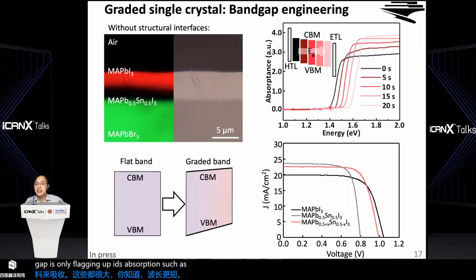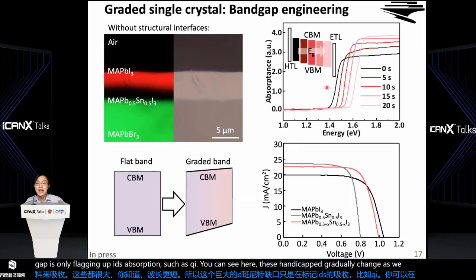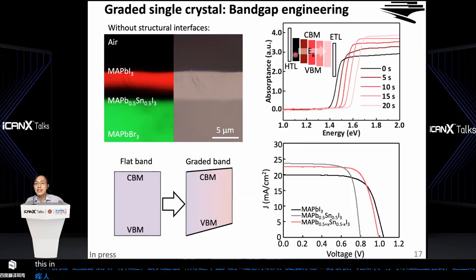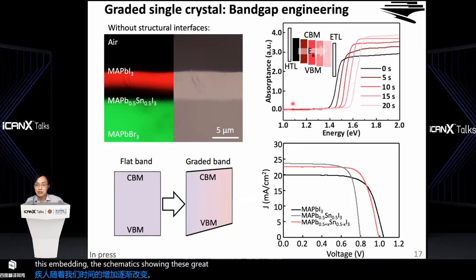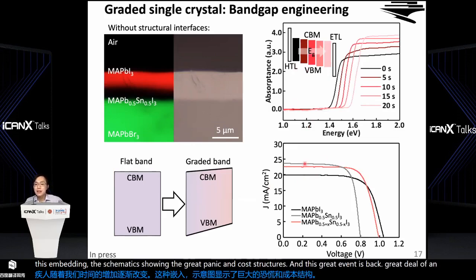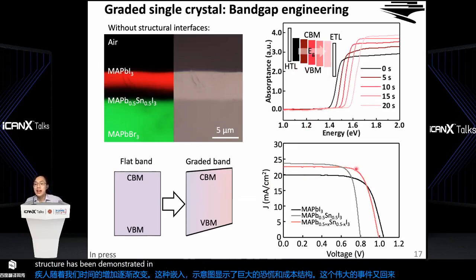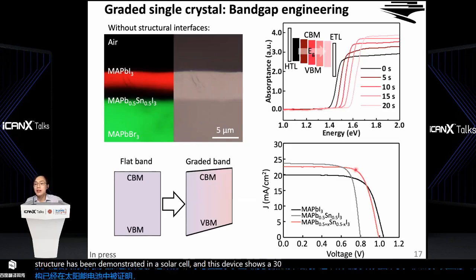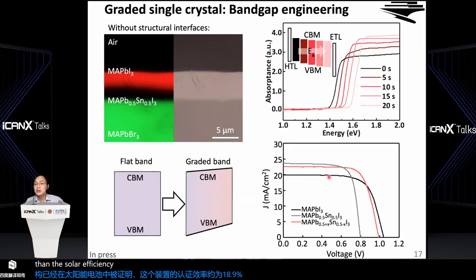You can see here this band gap gradually changes as we increase the time, and this embedded schematic shows these graded band gap structures. And this graded band gap structure has been demonstrated in a solar cell, and this device shows a certified efficiency of around 18.9%, which is higher than the solar cell efficiency using a uniform composition material.